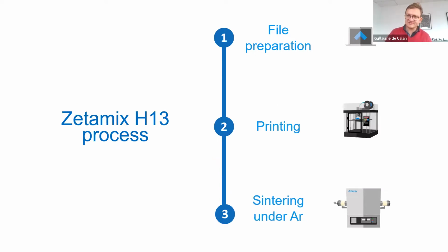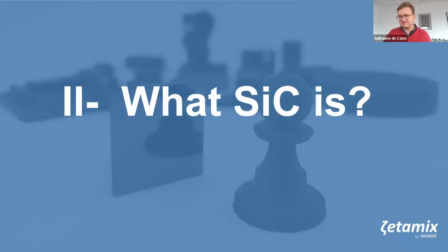If we talk about metal, it's slightly different. We don't have any chemical debinding - all the debinding is done in the furnace, which makes the process a bit simpler. Clearly you have 2 steps: you print, then you put it in the furnace, where you'll have debinding and sintering. However, the sintering needs to be done under protective atmosphere because, of course, if you don't do that, the metal will oxidize and you won't get a good material afterwards. For H13, it's done under argon. We also have a stainless steel which needs hydrogen, but it's a bit more complex.